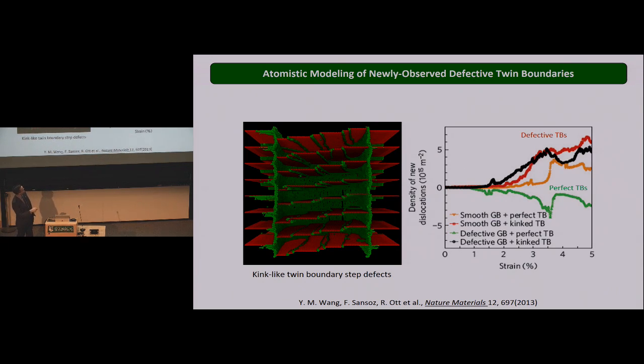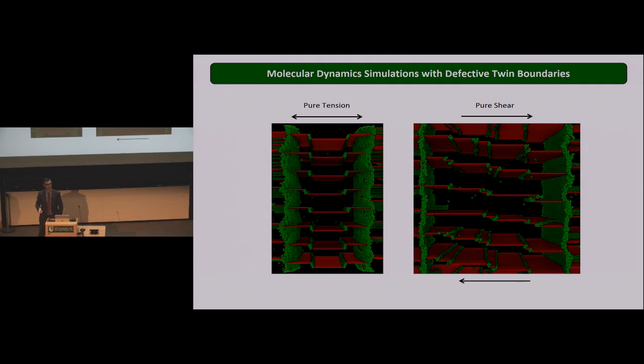So without defects, the perfect twin actually predicts from simulation a decrease in the dislocation density. Okay, so that's consistent with the fact that we don't accumulate new dislocations. And as soon as we introduce those very tiny defects along the twin boundary, each case shows that we increase the density of dislocation. So that's consistent with the X-ray diffraction experiment showing the accumulation of dislocation. All right, so let me show you some videos that will illustrate some new deformation mechanisms that result from the introduction of those kink defects.